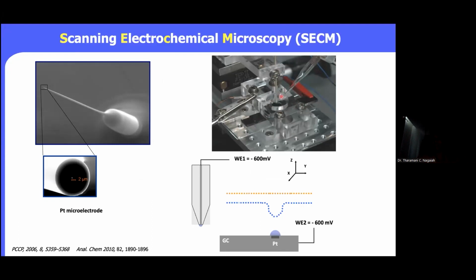And this is our reference electrode and counter electrode. Only thing is we are utilizing this platinum 25 micrometer platinum microelectrode, and we are utilizing the redox competition mode of SECM here. In the case of redox competition mode of SECM, you can see here, the sample on the surface, and we are applying a potential, that means we are polarizing the sample at a constant potential with respect to the oxygen reduction reaction, where it can convert to the water, and we are trying to apply a potential on the tip, and we try to monitor the current on the tip here.